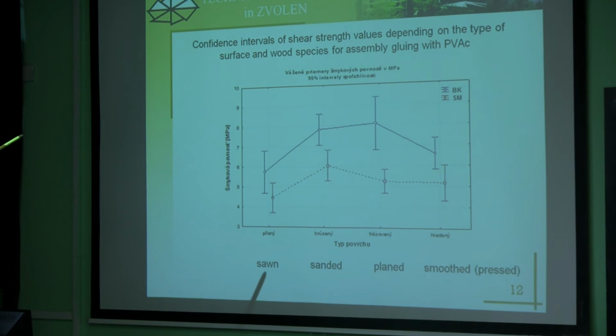These results are for one type of the surface. These results are for sanded type of the surface. These results are for planed type of surface, and these results are for smooth pressed surface, which is very related to thermowood as you used in your laboratory works. So here is the relation of the shear strength. Shear strength is here in megapascals, and from these diagrams we can see that the best results, the highest shear strength,